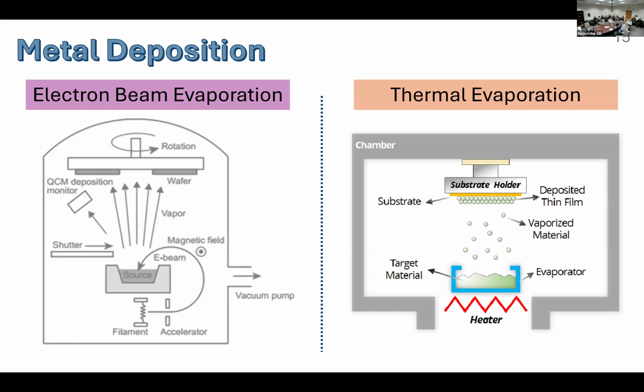Once we have that, we can go ahead and do our metal deposition. So the two most common methods used in this work are electron beam evaporation and thermal evaporation. So in electron beam evaporation, you have an electron beam, you point it at your source that will heat up your source. The evaporated material will then scatter back and deposit itself onto your material or your substrate. In thermal evaporation, instead of using an electron beam, you simply use a current passing through a metal boat containing the source material that you want. This current will heat up the source material, and then eventually that will, because this is in vacuum, rise up and deposit itself onto your substrate.